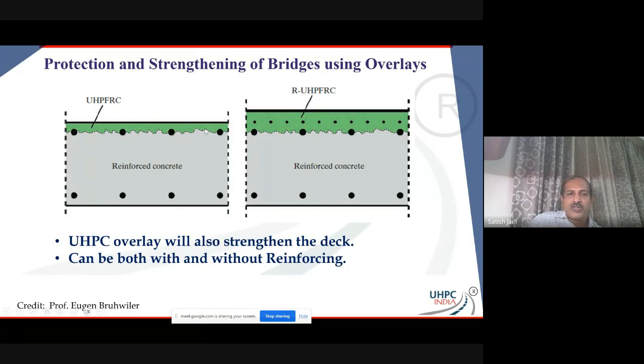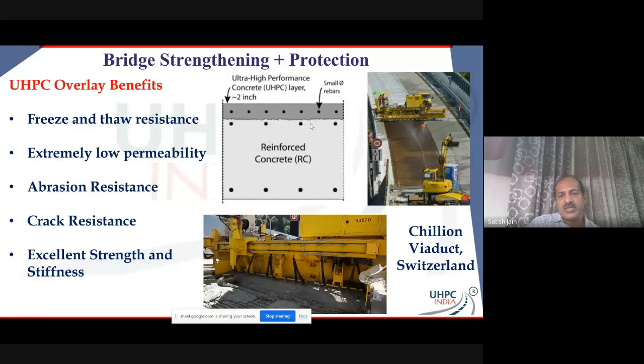So that's the beauty of UHPC. You see, it's a very nice roughening. I'm going to talk about the roughening process a bit, but you need to have a pretty good roughening process. On the right side, you may or may not require the rebar, but this is a typical strengthening project where even rebar has been put. The left side was about 30 in this particular project, and the right side was about 50 or so of UHPC. But it's a reinforced UHPC used for strengthening one of the bridges in Switzerland. It's a viaduct in Switzerland, Chillon viaduct, where a couple of inches of UHPC was put in.